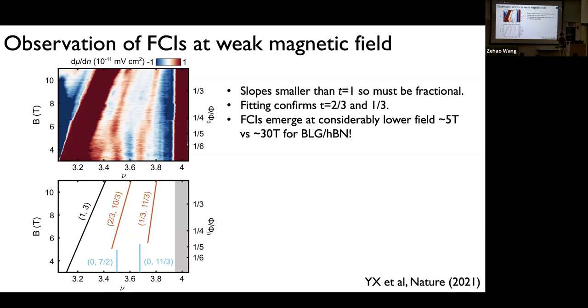When the data came in, without really analyzing it, we knew we were up to something, because the slope is very different, and it's between 0 and 1. It's got to be a fraction. And when you do the careful analysis of the slope, we found that one of them is 2/3, one of them is 1/3. These are very familiar numbers for us when you talk about, say, the fractional quantum Hall effect.